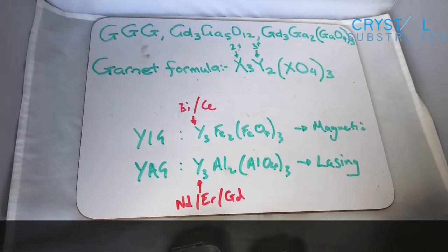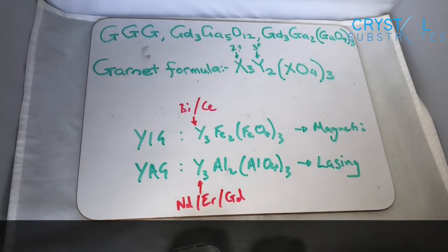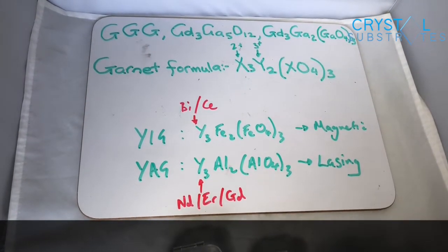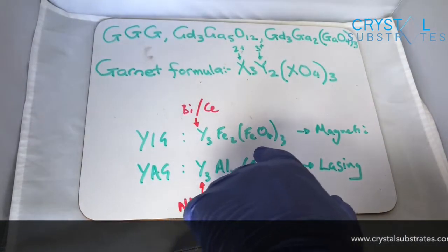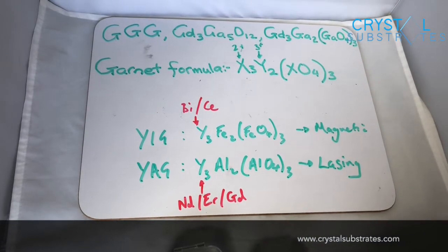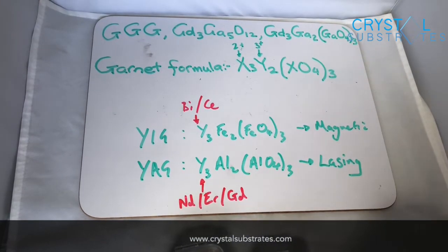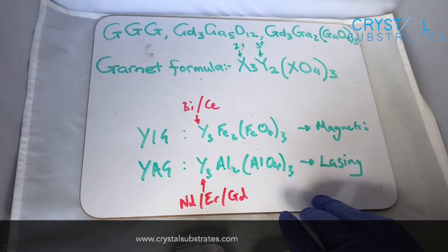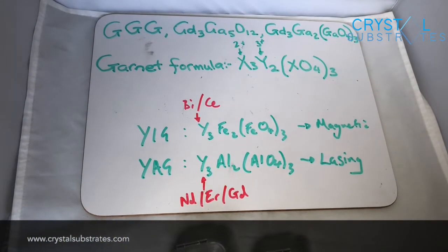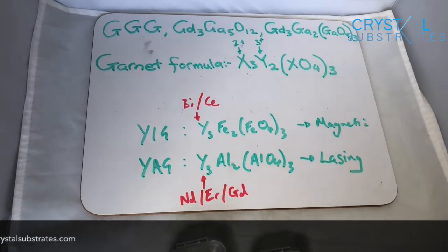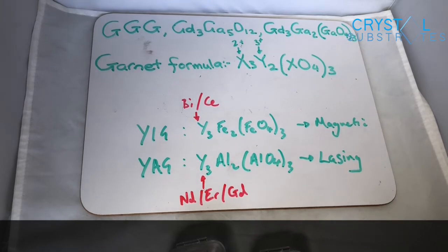What you'll notice is that these become quite complex oxides to grow in the solid form, so it lends itself really nicely to pulsed laser deposition, where you can replace the cations very easily in your target, and then they'll transfer over into your thin film material, with maybe the exception of bismuth, which can be transferred over at a lower rate. So often the targets that we use will require some excess bismuth in them.